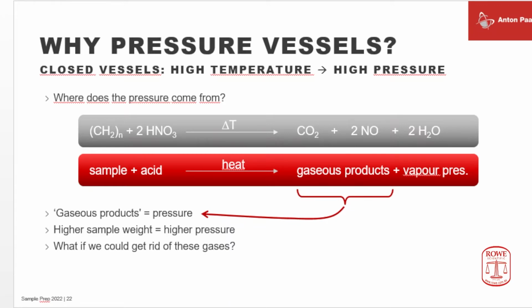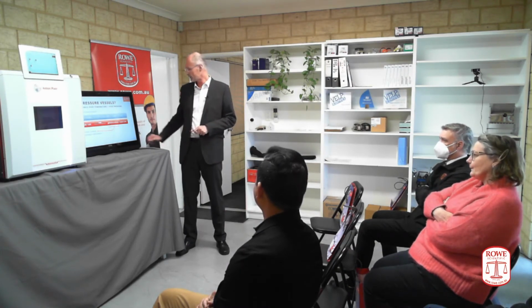Gaseous reaction products will occur, CO2 from the carbon, nitrous gases from the decay of the nitric acid, and there will be some residual liquid which develops some vapor pressure. So the pressure inside a closed reaction vial is the addition of the partial pressures of the gaseous reaction products and the vapor pressure of the liquid. Now, what implications does that have? Gaseous products, that's the things that produce pressure. And it means the higher our sample weight, the more CO2 we are producing, the higher the pressure will get. This is a little bit the downside of closed vessel digestion.